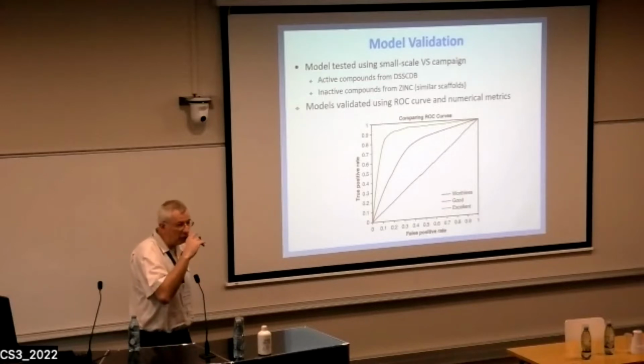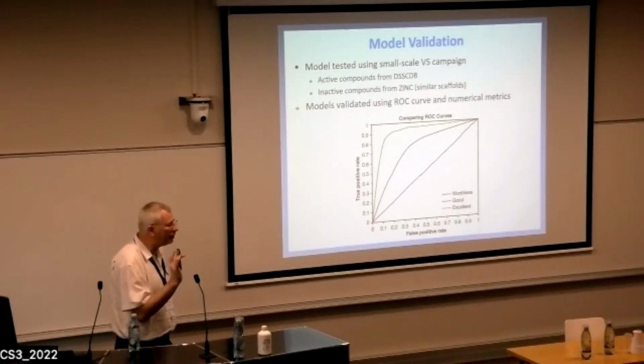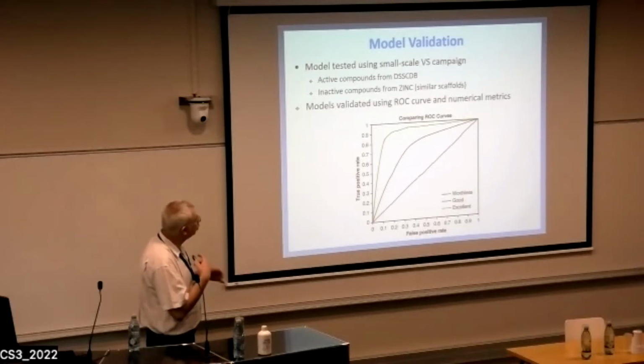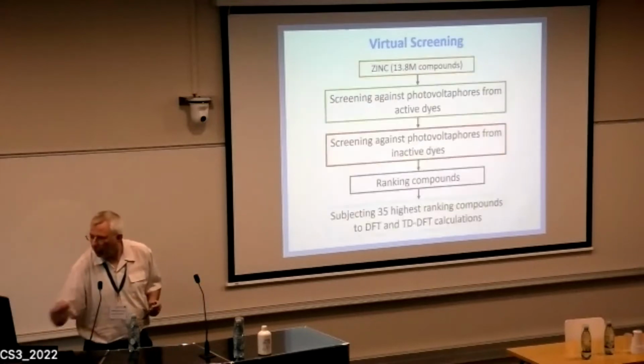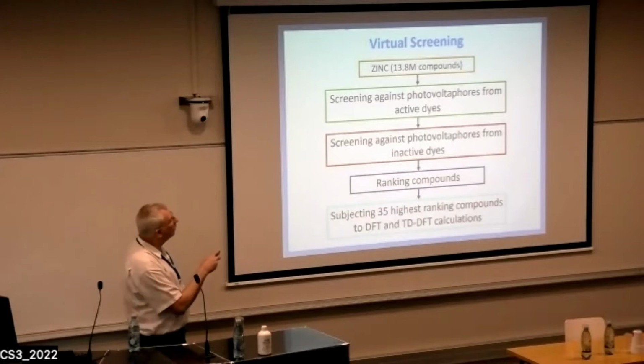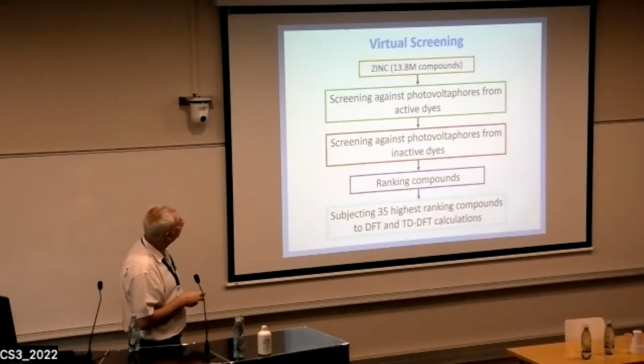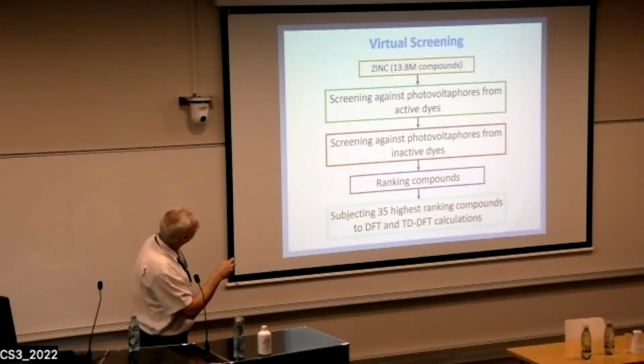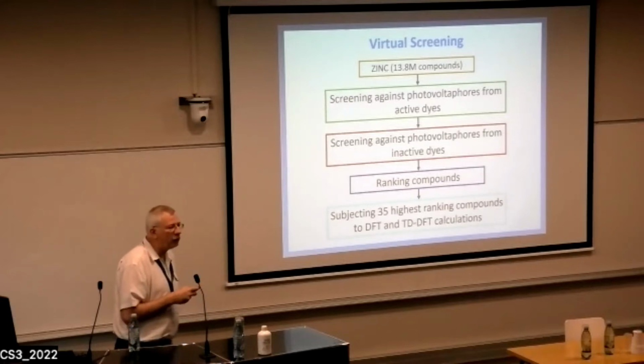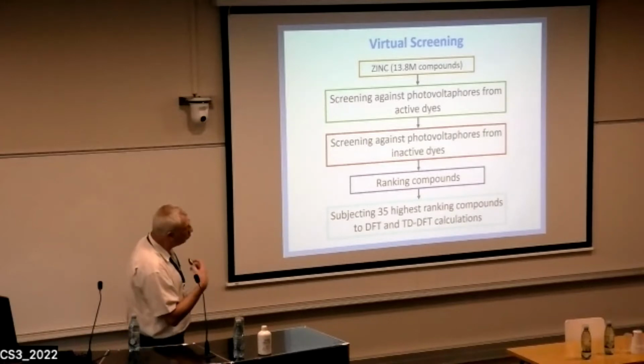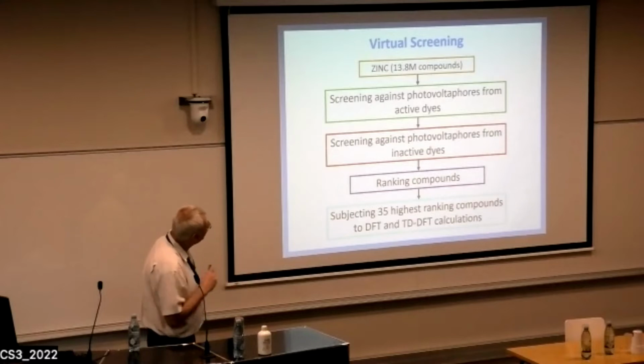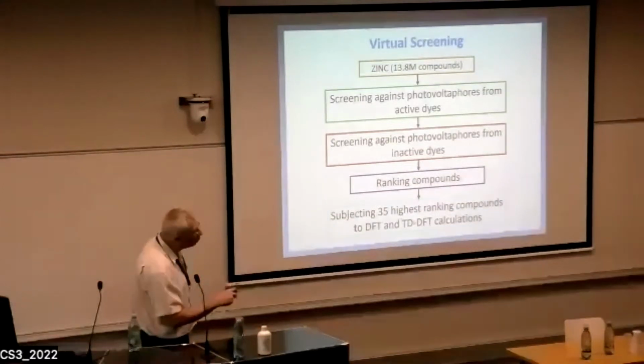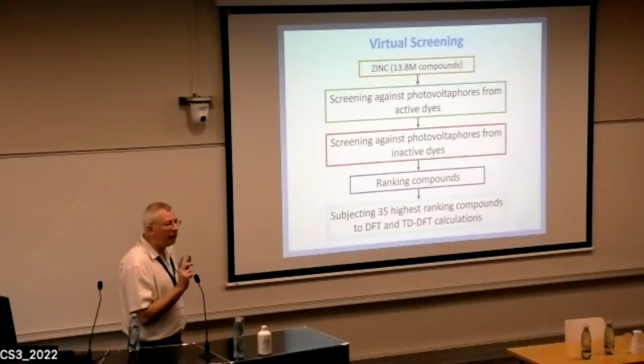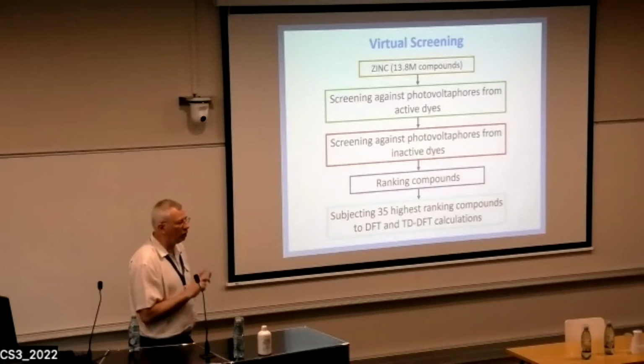I think we developed some 100 models. We looked at the 18 models which we liked. We did the virtual screening. We took the ZINC database, containing about 14 million compounds. We screened against the active dyes. We then removed compounds by screening against inactive dyes. We ranked the compounds. We selected 35 compounds, and then we submitted them to high-level ab initio calculation.